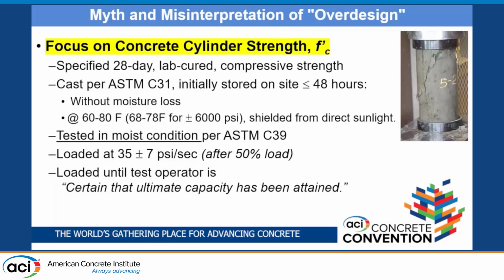And then tested in a moist condition. If that cylinder looks dry and dusty and light gray, it shouldn't be tested. It needs to be tested moist and loaded at 35 plus or minus 7 psi per second after the first 50% of the load. If it's a late Friday afternoon and the boss at the testing company says, I'll tell you what, as soon as you finish up all those cylinders, head home for the weekend. Man, it's going to be load, bang, and that's good news for the contractor. A late Friday afternoon cylinder break, those numbers are going to go up.